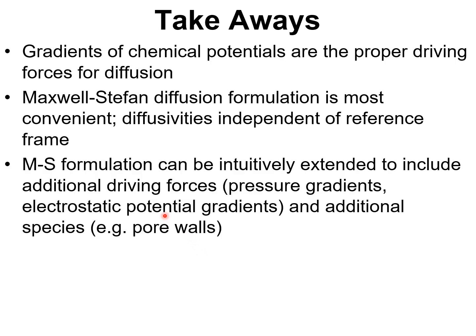Here are the major takeaways from this presentation. The gradients of the chemical potential are the proper driving forces for diffusion. The Maxwell-Stefan diffusion formulation is the most convenient one. The Maxwell-Stefan diffusivities are independent of the reference velocity frame. The Maxwell-Stefan diffusivity has the significance of an inverse drag coefficient. And an important fact is that the inverse drag coefficient D12 is independent of the reference velocity frame.